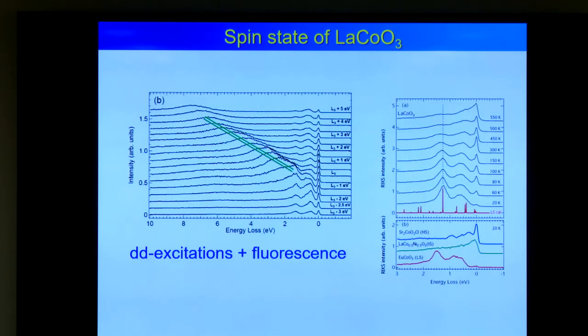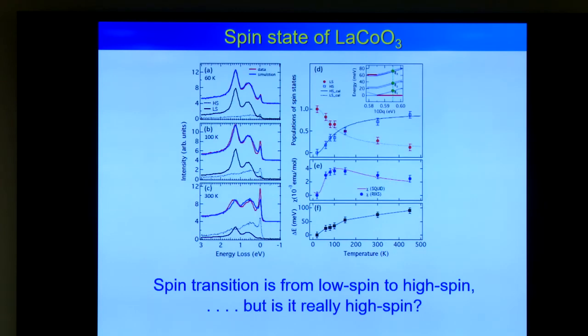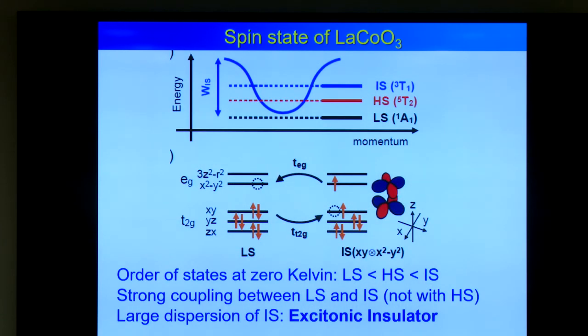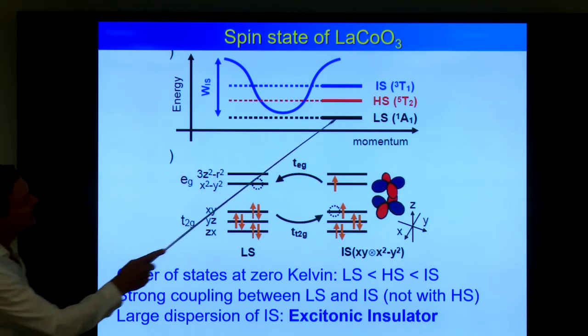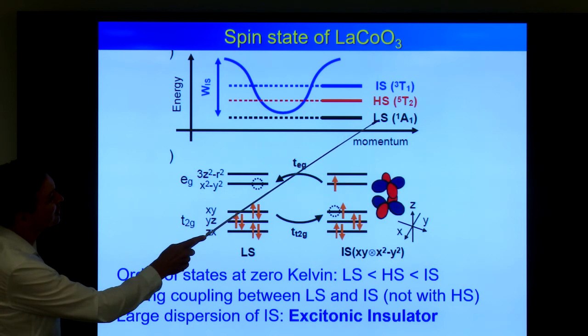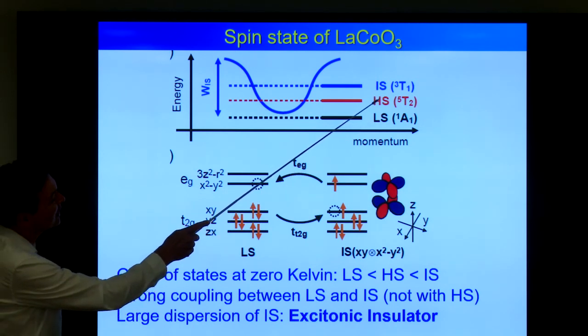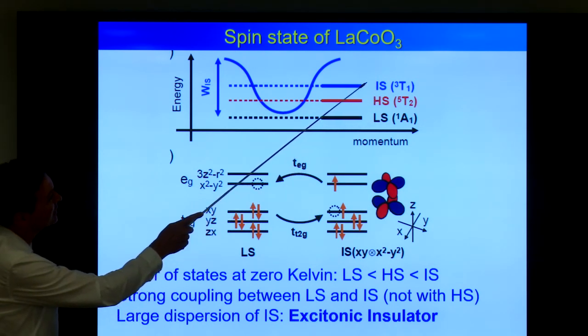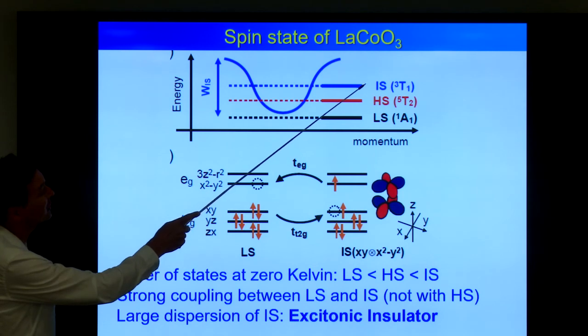That's interesting, but you can read that back in the paper. But that's not the whole story, because this is the energetics now. So you have low spin at low temperature, and then it switches to high spin at high temperature. But there's also intermediate spin, and that's relatively close. It's 0.2 or 0.3 electron volt away.